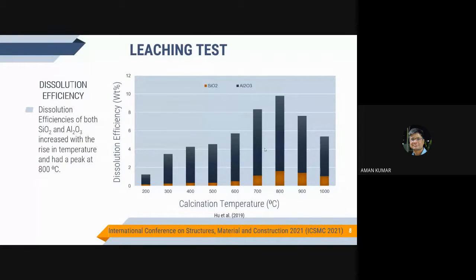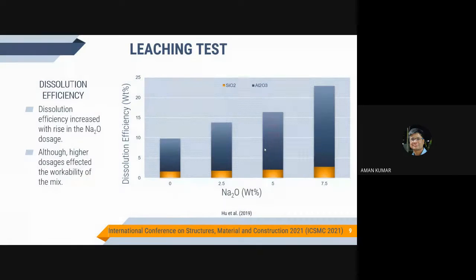Leaching test was also performed to evaluate the activity of Al2O3 and SiO2 with varying calcination temperature and Na2O dosage. It was noted that the dissolution efficiency reached a peak for both the compounds at a calcination temperature of 800 degrees Celsius and decreased when the temperature was further increased, while the dissolution efficiency kept on rising with the addition of more Na2O. A rather higher dosage impeded the workability of the mix. Therefore, a balance is required for its optimum utilization for a certain application.